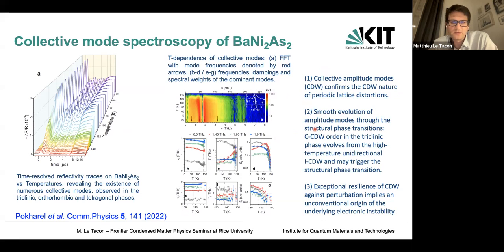But what they find is that there is a very smooth evolution of those excitations across the different phase transitions. So in a sense, you go from the incommensurate charge density wave to the commensurate charge density wave continuously. And when the commensurate charge density wave forms, then it distorts the system. It triggers the triclinic distortion, in a sense, by pulling things along the c-axis, if you like. That's how I understand it.